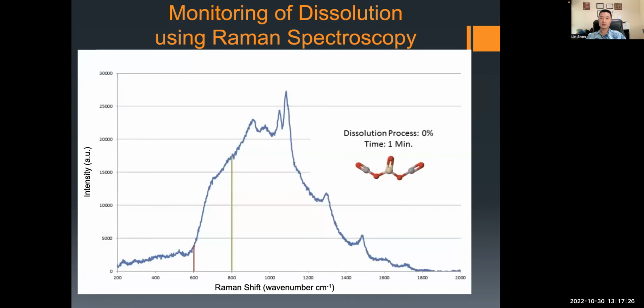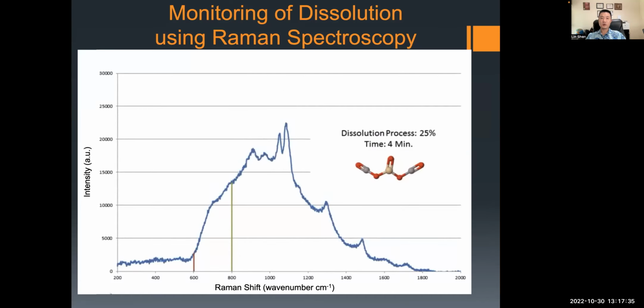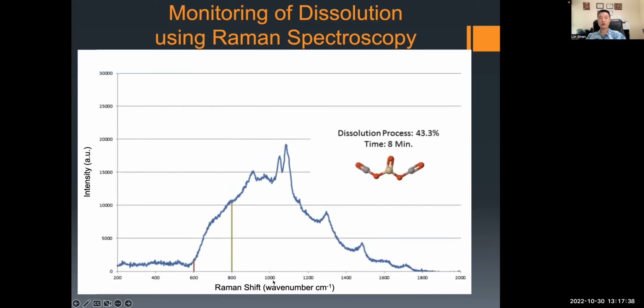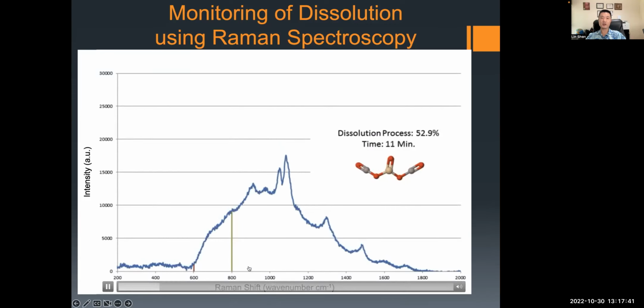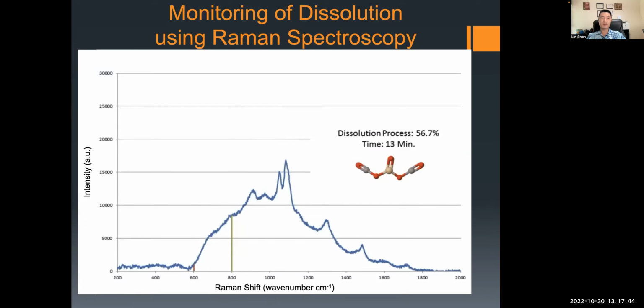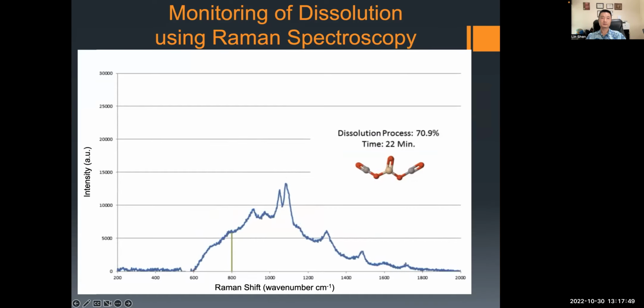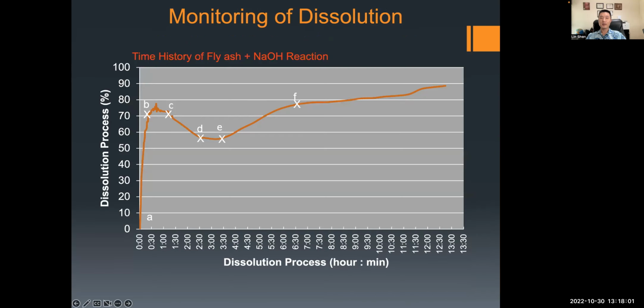This video shows dissolution of fly ash in sodium hydroxide solution for the first 24 hours. The dissolution speed changes over time actually, and sometimes even reverses its direction in certain phases. So you can see it going down, sometimes even going up. And here shows the dissolution percentage on the y-axis versus dissolution time.